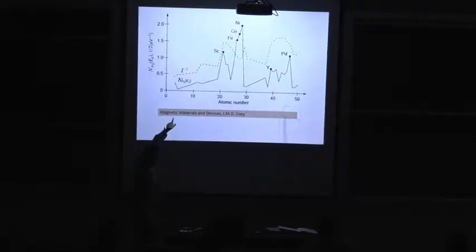So if you observe, iron, cobalt and nickel have their heads sticking out of this graph. So the Stoner criterion is satisfied for these elements. Scandium is really close. So if scandium had a little bit higher density of states, it might become ferromagnetic. Palladium is exceptionally good.